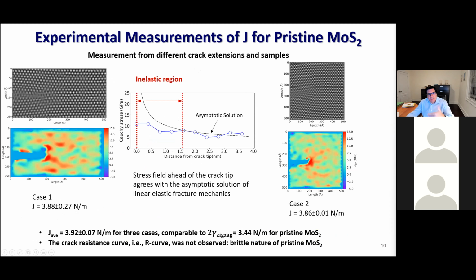And here are two instances, two experiments, where different crack lengths have been computed, and you see that the energy release rate, the J integral, computed by an area, in this case, is quite close, and here is the error coming from fluctuations. So you see that the stresses that you obtain have fluctuations, as you would expect, and if you look in detail at the image, the degree of defocusing is not uniform. And this is because these are very flexible membranes, and thermal motion will introduce this oscillation and defocusing, and the degree of defocusing translates into the resolution in the displacement measurement.